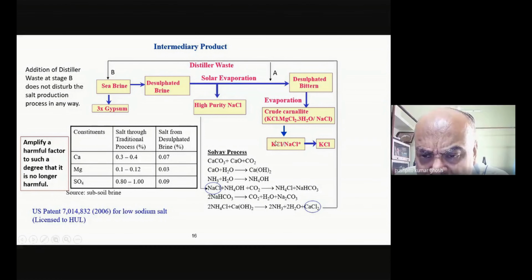Now, what people have been doing up till now when they're making low sodium salt is they take pure KCl and they buy pure NaCl and they blend the two and they make a NaCl-KCl mix. Now, what we said is, why not use this intermediate itself as low sodium salt? Why should I even do this? And what that did is that it crashed the price of production of low sodium salt, and that's the technology that was licensed to Unilever. I don't know if they are still practicing it, but at that time they told me that in all their Knorr soups, etc., they were actually using low sodium salt. And so there might be a little bit of this technology every time you have some Knorr soup.